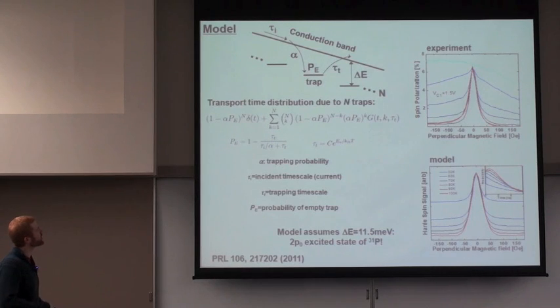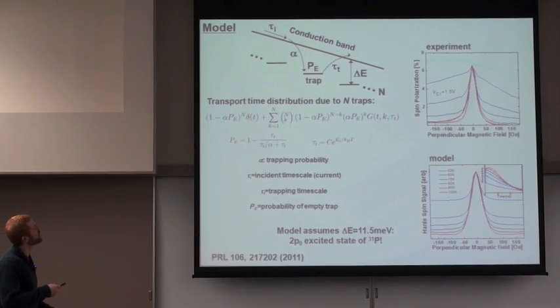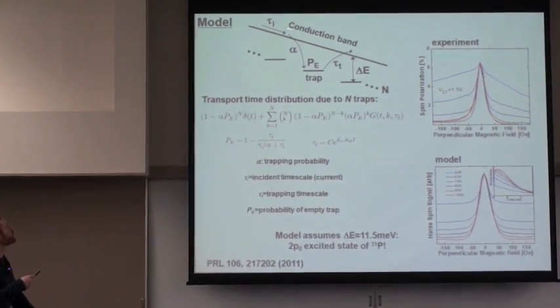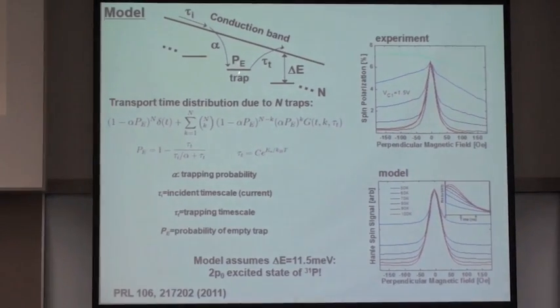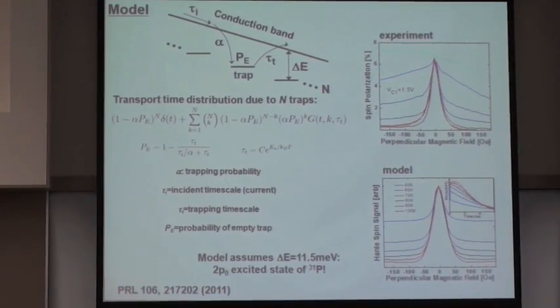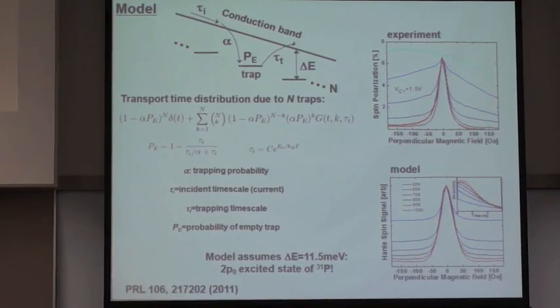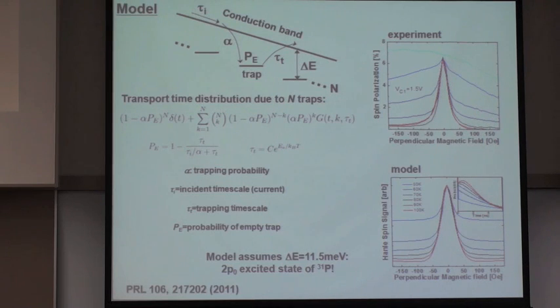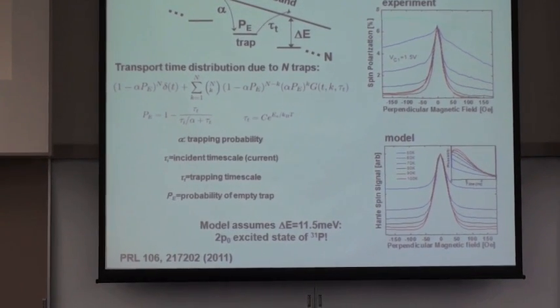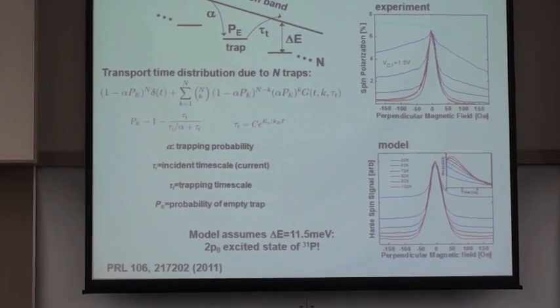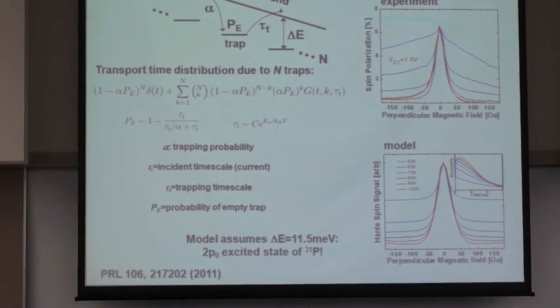Now, if we essentially sum up over all the contributions from all the possibilities for electrons to be trapped in one of these impurity states and then come out any number of times, given some fixed number of traps, then we can model this effect. And what you see is that we can recover this sort of time distribution due to the fact that the re-emission process is, of course, thermally excited.